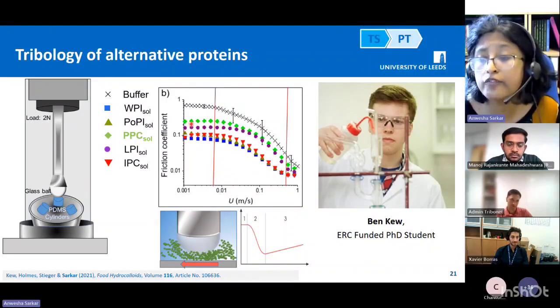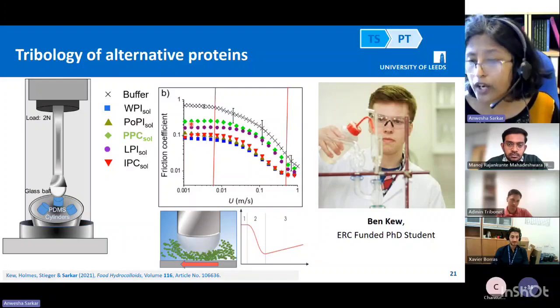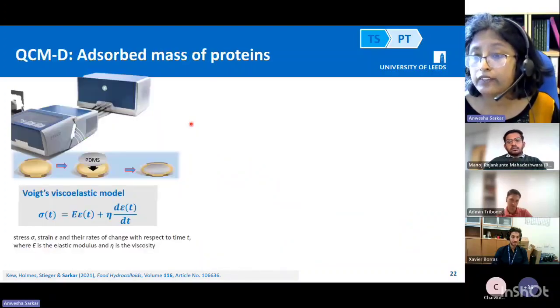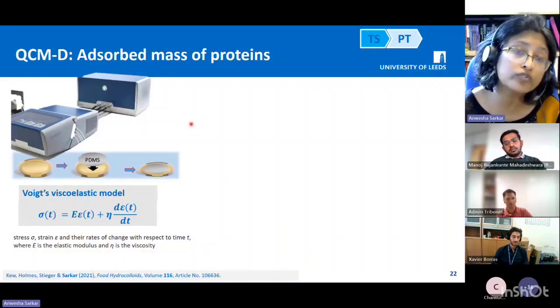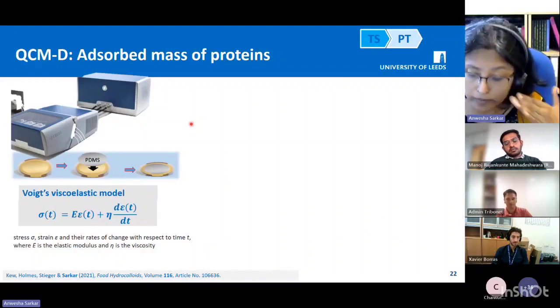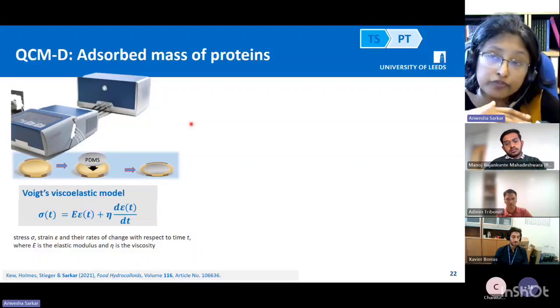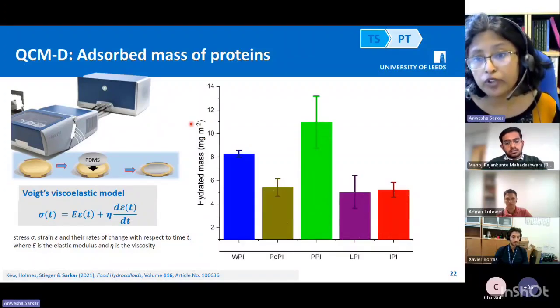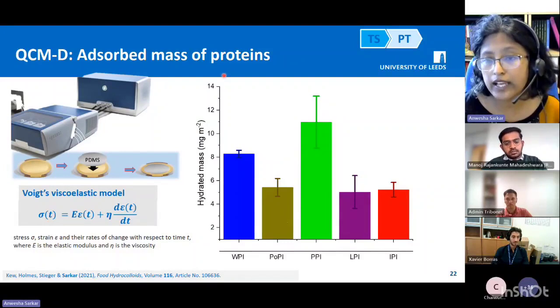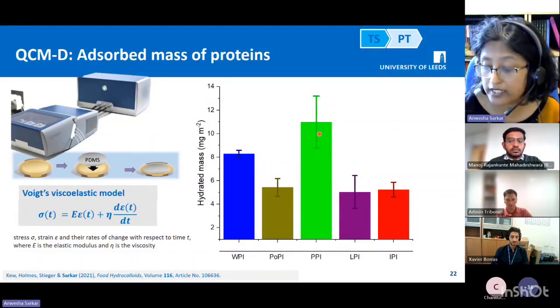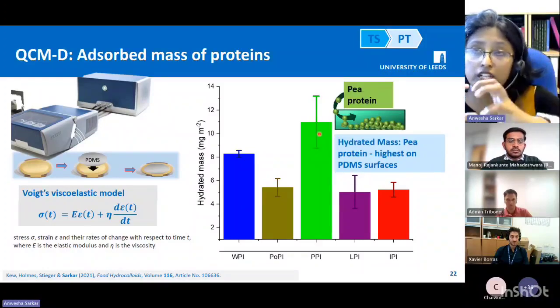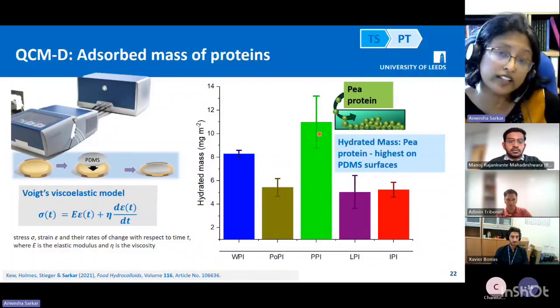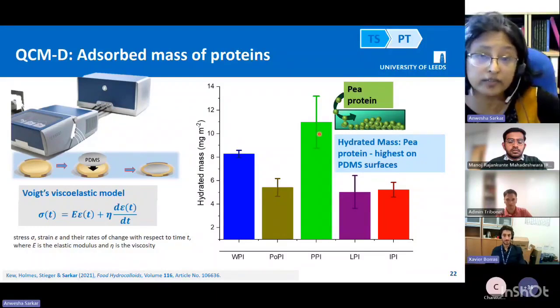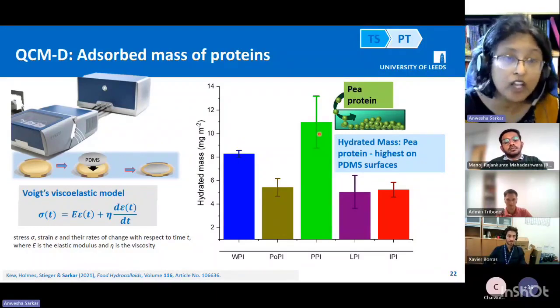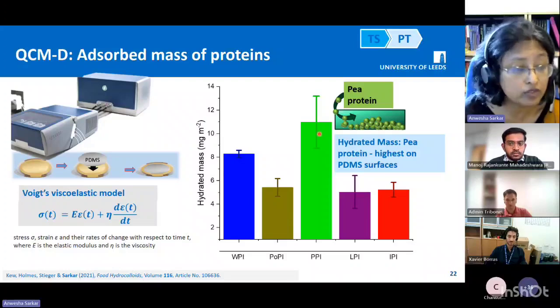So what we did, we wanted to understand why is it happening like that? And we did some QCMD, which is quartz crystal microbalance with dissipation measurement, to understand the film formation. And what we observed is that pea protein has a very, very high amount of adsorbed mass when it adsorbs, and it forms essentially a very interesting cross-link structure because of jamming of these particles due to aggregation. So that's the reason why it was giving so high friction.